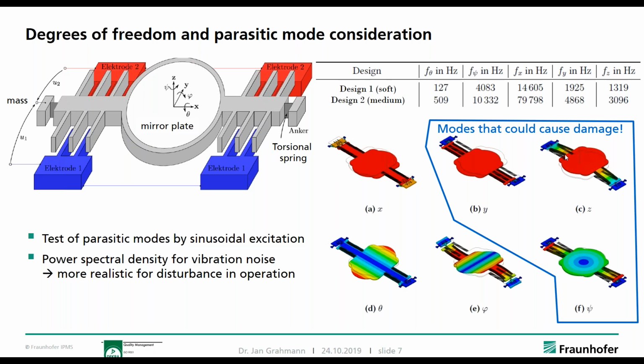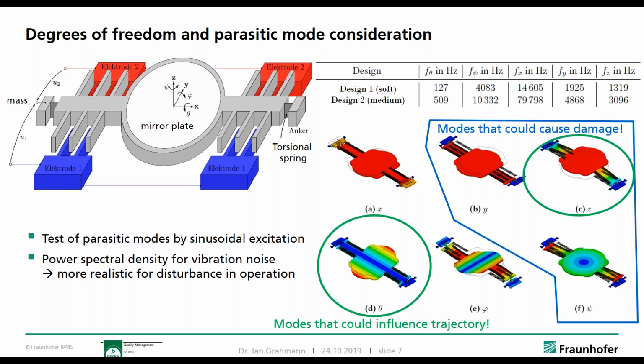Another one is that mode shape, in Z direction, which means the mirror plate moves up and down, which you also don't want to have. And that could, for example, break the torsional springs of the scanner. And another one shown here is basically a mode where the scanner is turned around its Z-axis, and therefore you get, again, a movement of these comb electrodes towards the other electrode, which could also be damaging. So you definitely want to avoid these modes. Respectively, they should not be excited to a degree where they can damage the scanner. That is one point to look at. The second one is what are modes that could actually influence the trajectory precision that I showed on the slide before.